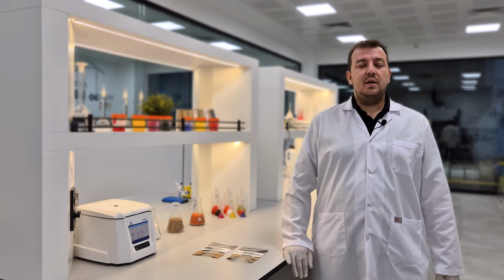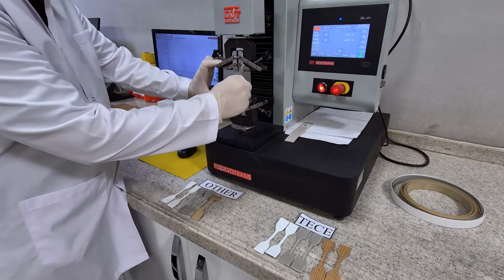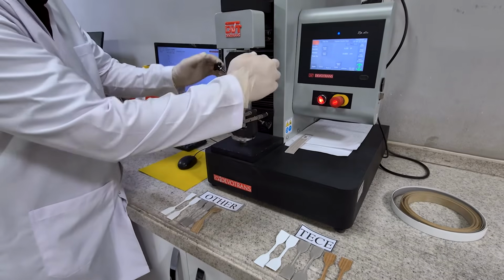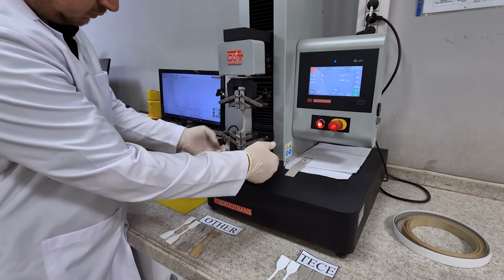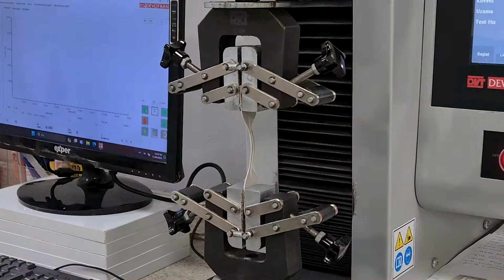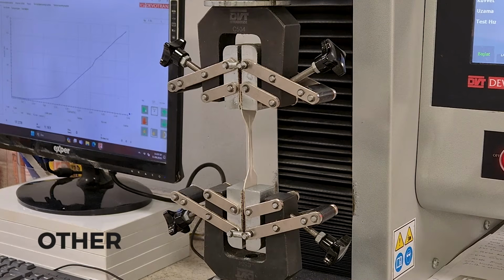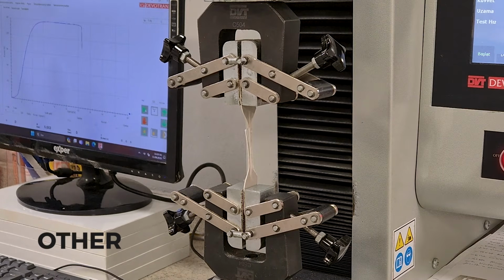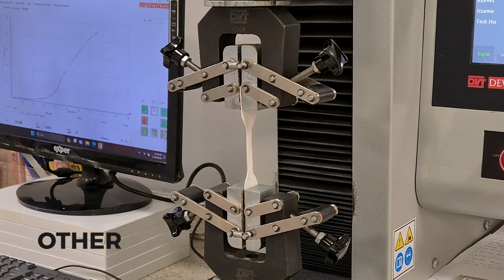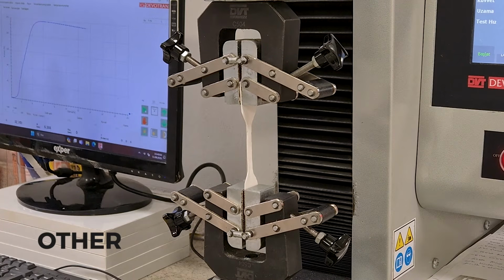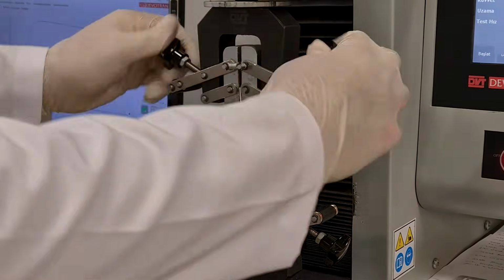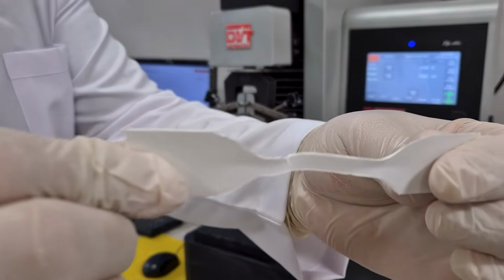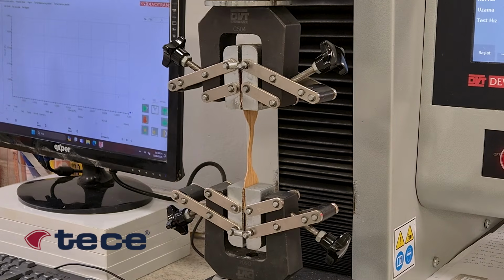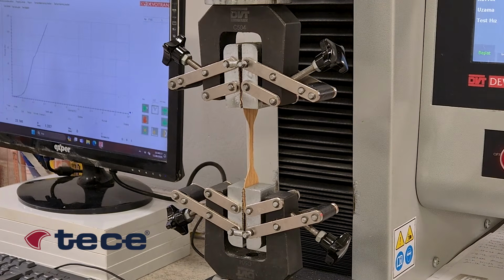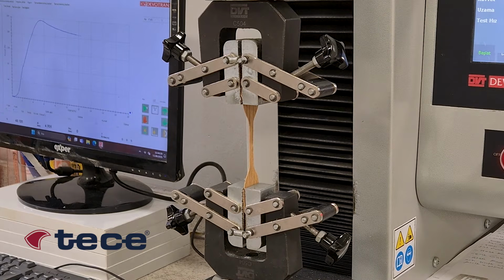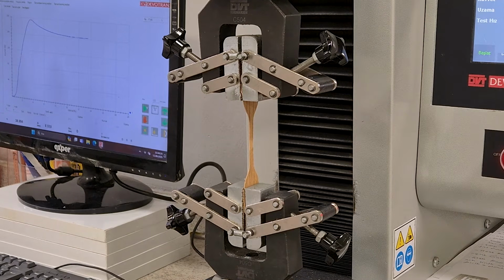Now we move to the tensile test. We will carry it out according to ISO 527 standards on samples cut in a bow tie shape. Let's see the result. The results are clear. The other cheap edge banding breaks under very low force. This is because it contains too much filler and the plasticization process was not fully completed. In the Tece edge banding, the use of high-density polymer gives a much higher strength value. This ensures a strong polymer.